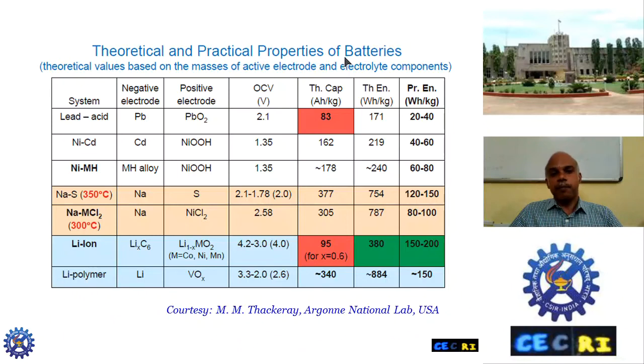So the theoretical and practical properties of batteries: if we compare with lead acid, the theoretical capacity is only 83 ampere hour per kilogram, whereas for lithium ion, if you take for example LiCoO2, for removal of lithium, x is 0.6, you can get 95 ampere hour per kilogram, as well as the practical energy density obtained by lithium-ion batteries is much higher than the lead acid batteries.